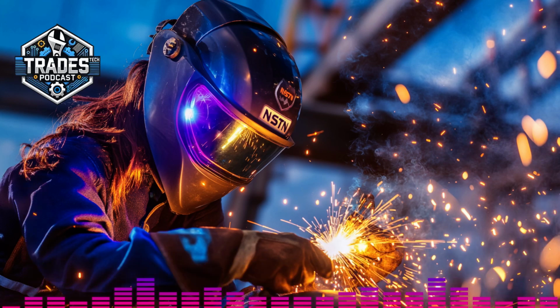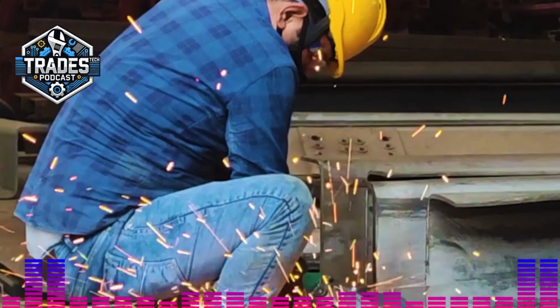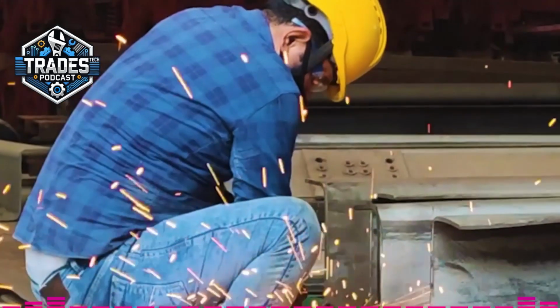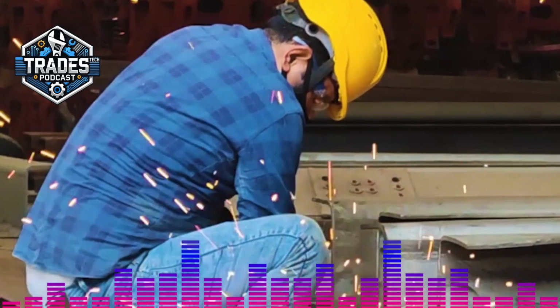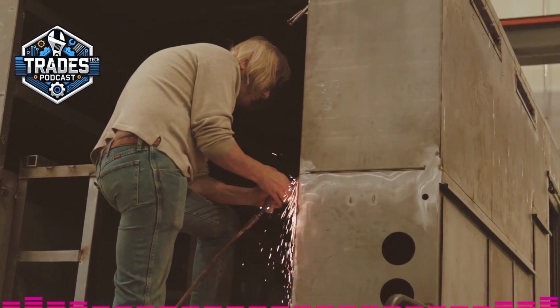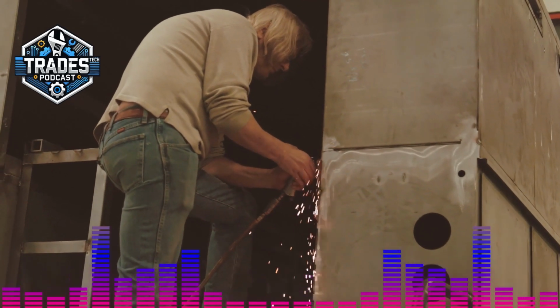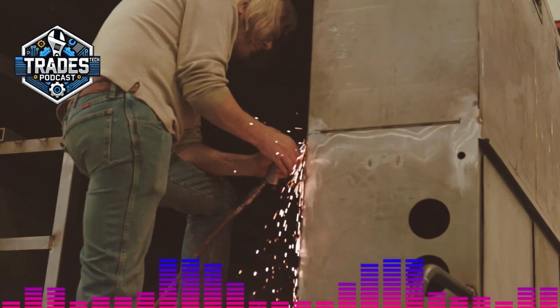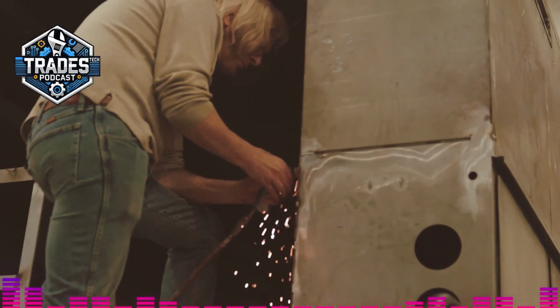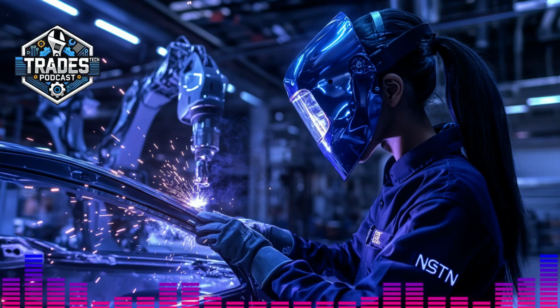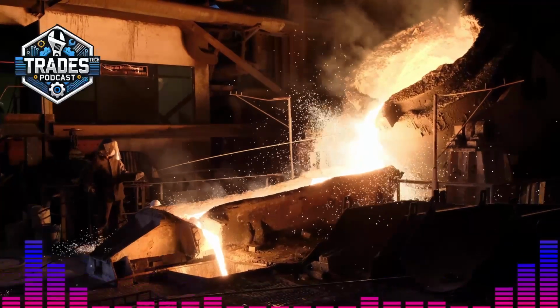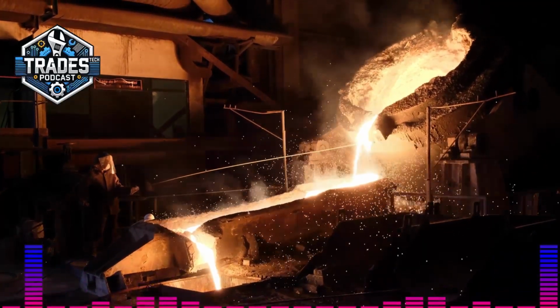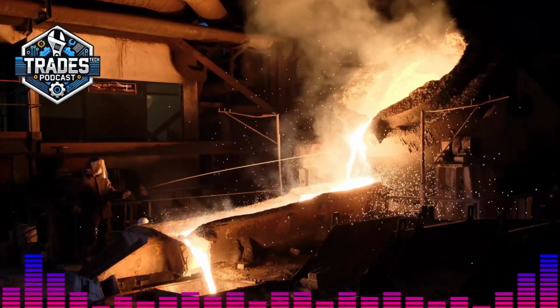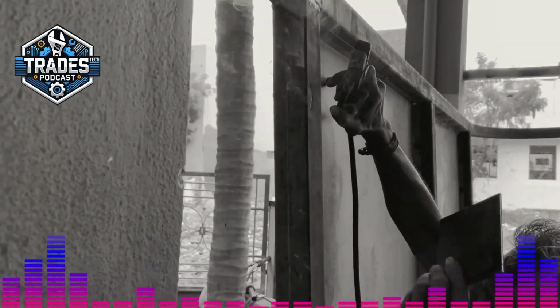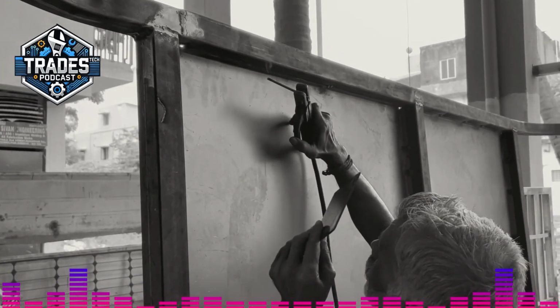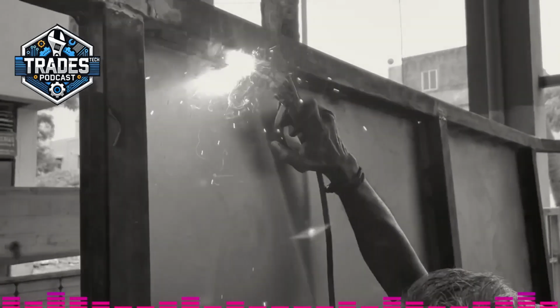And those environmental conditions are precisely why FCAW, especially FCAW-S, is so prevalent in outdoor and industrial settings. Tori, why is this process so much more forgiving in wind or on less than perfect surfaces compared to, say, MIG welding? This is where FCAW really earns its reputation as a field workhorse. The shielding generated by the flux, particularly in self-shielded wires, is much more robust and less easily dispersed by wind than the external gas used in MIG welding. Imagine trying to maintain a stable gas shield on a windy day at the top of a new high-rise or on a bridge deck over a river. It's incredibly difficult with MIG. The wind just blows the gas away, leaving your weld vulnerable to atmospheric contamination, primarily oxygen and nitrogen, which leads to porosity and a weak, brittle weld.